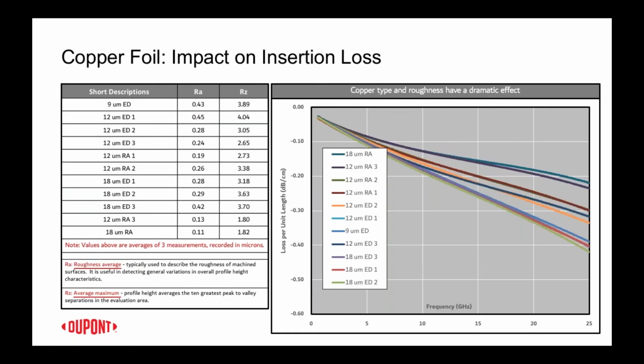So in this next slide, we're showing the copper foil impact on insertion loss by way of using a standardized test vehicle. This is the same design, same line width, same impedance, same dielectric height for a 50 ohm line, same dielectric constant in each case. And the only thing varying is the type, whether it be different types of rolled or electrodeposited coppers, and the weight of the copper. So we've got variants that are 18 microns or 12 microns in thickness.